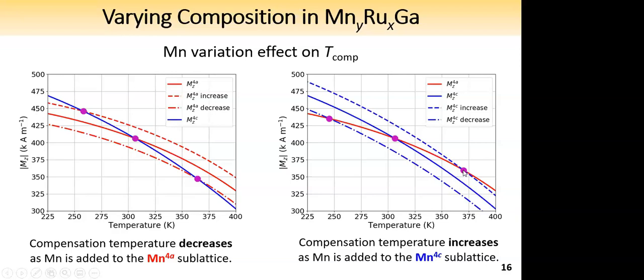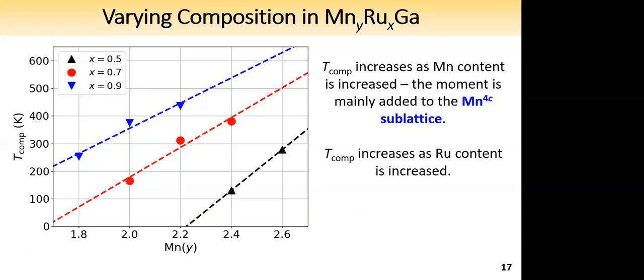So now, because we have an idea how T-comp will vary as manganese is varied, we can look at the data and determine which site is being manipulated. So here I am showing the variation of T-comp for 3 ruthenium series with x equals 0.5, 0.7, and 0.9, and I'm varying manganese shown on the x-axis. As you can see, as manganese increases in every series, the T-comp also increases. And as I've mentioned at the beginning of the presentation, increasing ruthenium content also gives an overall increase of the T-comp. So this is all consistent, and now we know we're mainly affecting the 4C sublattice.